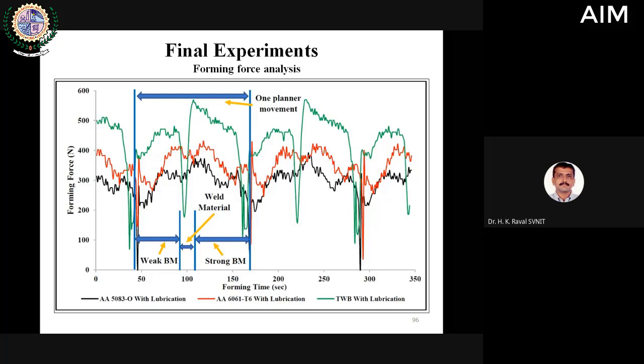So that pattern is different from the pattern recorded for the forming of the single blank. Still, the investigation is on. We are unable to give a conclusive remark right now on why the force at the weld junction is dropping. Why is it not increasing? Why should it not increase? Because weld is always considered a strong joint compared to the weak material or strong material. But sometimes it is observed in tensile testing that if welding is not properly done, then weld strength may not be comparable with either the weak material or strong material. Hence, that might be the reason for some drop in the forming force.